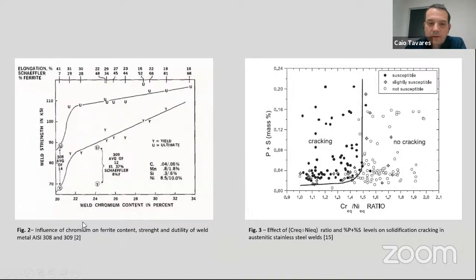Here are some examples of the effect of this delta ferrite. This graph was created by Schaeffler. You see the amount of delta ferrite: when we increase it, the strength of the stainless steel increases. This other graph is a correlation between the chromium equivalent and nickel equivalent that you will see later. This relation basically defines the amount of delta ferrite. When we have a low ratio of chromium to nickel equivalent, you have a high susceptibility to cracks in the stainless steel, and after a certain amount, you don't have this issue anymore.